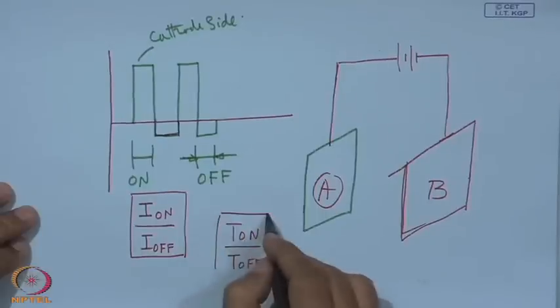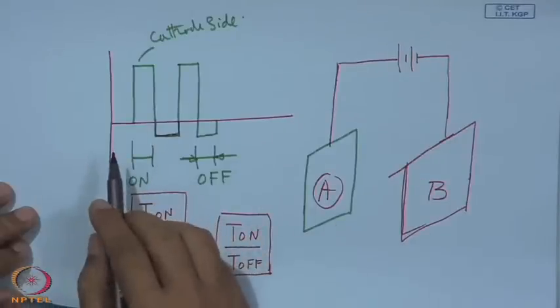Now, it is also reported that by this process of this pulsing technology, it is possible to have remarkable improvement in the quality of the coating. This nickel coating or nickel cobalt coating or similar materials which have all the required properties as a metal, but when it comes like a deposit, there we lose their property, as we have already mentioned: a porous structure with hydrogen embrittlement, we have non-uniformity, we have a globular formation, a lot of imperfections are incorporated, and last but not least, large grain, enlargement of the grain. So, it looks like all discrete materials are put together with a lot of air pockets in between.